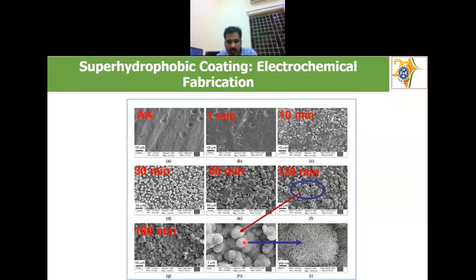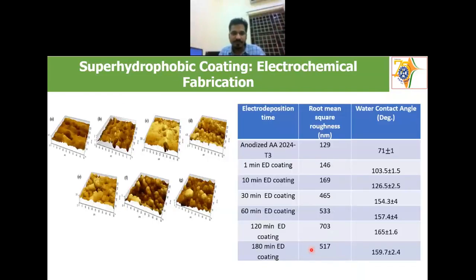And then on each one structure, if you see here, a rice husk structure, you can see on top of it a kind of micro nano texture, because on a micro particle here, I'm able to create a kind of nano structure. So this micro nano texture is going to give you the super hydrophobicity, because when the water molecule is sitting on these types of surfaces, it is not exactly sitting on that surface. Instead, the air is trapped in between these grooves, a typical lotus leaf effect.